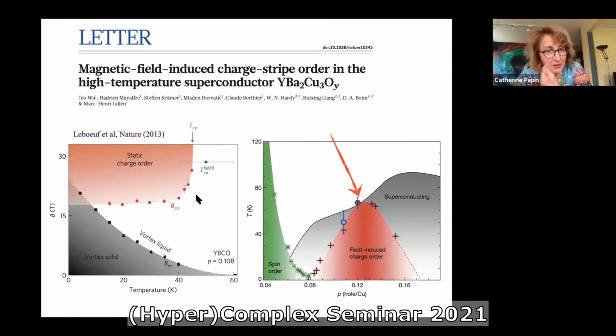Okay, the effect of magnetic field is very unusual in this material. As I said, charge order is stabilized by magnetic field. Here is an ultrasound experiment showing it. You see, with magnetic field above 17 Tesla, you stabilize three-dimensional, now, charge order, uniaxial. And what is very unusual is to see this temperature. Temperature is non-existent, so it's flat. So it goes from superconductivity, coexistence, but charge order is going poof like that in one way with no temperature dependence.